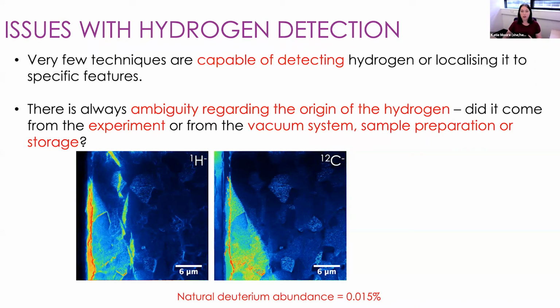Now, the reason we're interested in looking at deuterium and using deuterium in our experiments is that the natural deuterium abundance that we find in everything around us is only 0.015%. So very, very low levels. So if we're putting our sample into water containing 50% deuterium, for example, then any deuterium that we detect in our sample pretty much comes from our experiment only.